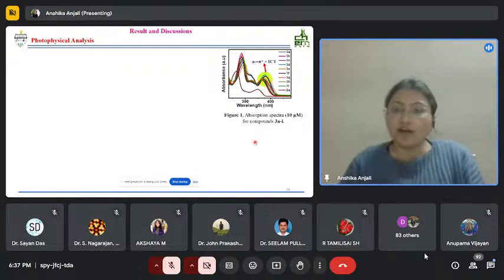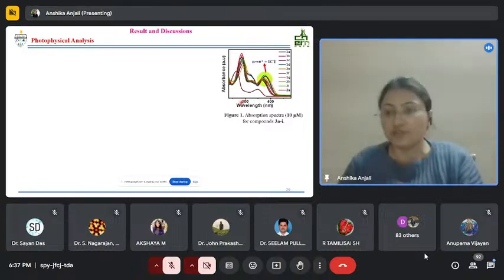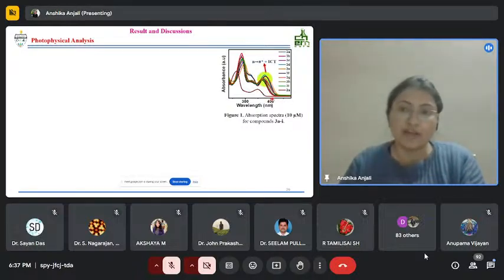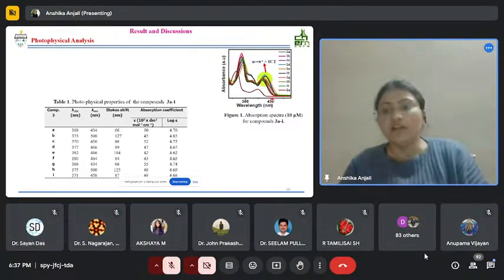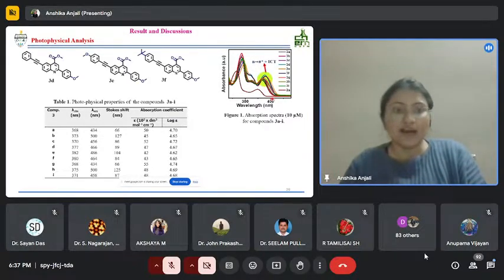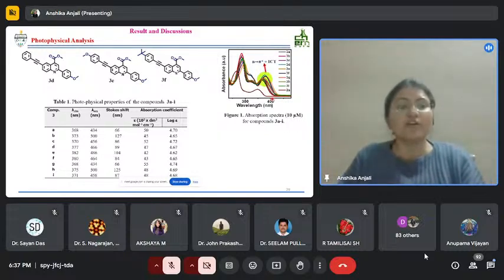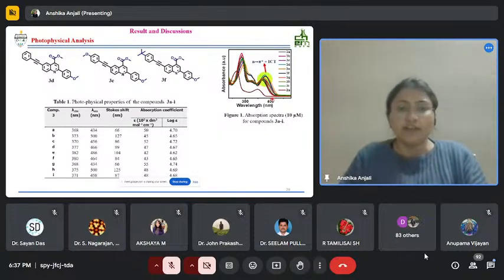So in the absorption spectra, we have observed a sharp peak from 250 to 300 nanometer, and a shoulder band from 300 to 350 nanometer, which corresponds to pi to pi star transition. Then a lower energy band from 350 to 400 nanometer, which corresponds to n to pi star transition. These compounds have also exhibited intramolecular charge transfer effect, and here the higher ICT effect was observed for compounds 3D, 3E, and 3F. It might be because of their extended conjugation due to the presence of this 4-methoxyphenyl group.